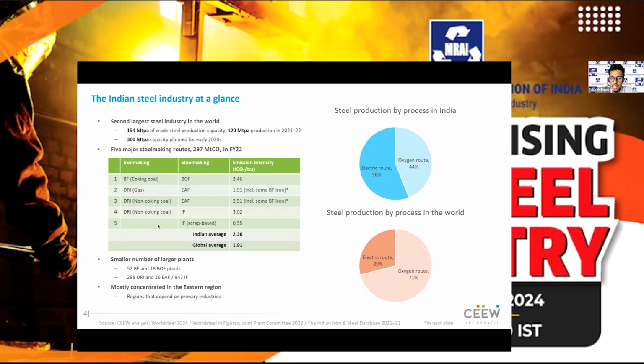Now, based on our analysis of the processes and the amount and types of raw materials that go into these processes, you can see the emission intensity of the processes on the table. So the DRI-IF process, which is primarily dominated by the small players, is obviously going to be the highest one, with around 3 tons of CO2 for every ton of crude steel that is produced. The BF-BOF process as well is quite emission intensive, around 2.5.